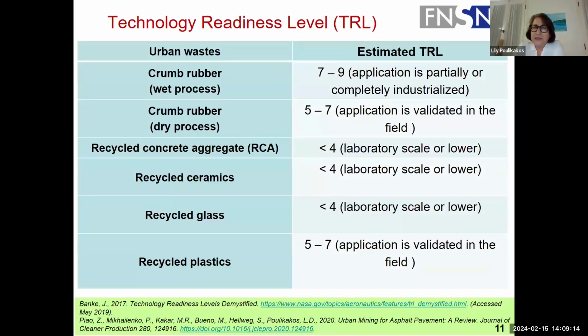However, the technology readiness level for these different kinds of materials is not the same. So we've looked at this sample of the materials, and for example, we see the crumb rubber using the wet process has a very high TRL level. We estimated it to be from 7 to 9, and that means the application is partially or completely industrialized. However, there are other types of waste materials, such as recycled glass, with a low TRL that indicates the information is only at the laboratory scale.